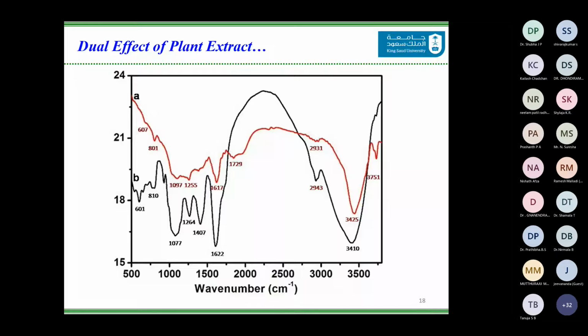And in order to see to it that we don't have any residual plant extract, these nanoparticles were washed several times and centrifuged at high speed so that any traces of unbound plant extract on the surface of the nanoparticle would be eliminated from the system. We should be able to remove it completely, and we should get only the signals from the plant extract that is bound on the surface of the nanoparticles. So efforts were put in just to see to it that we don't have an error.